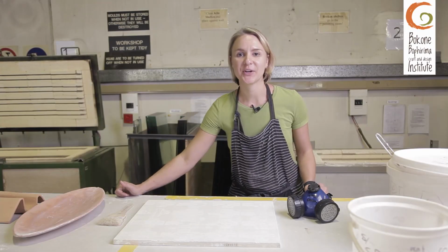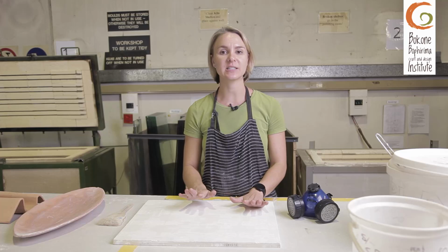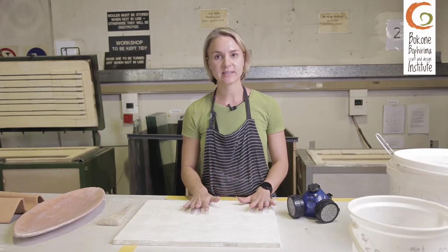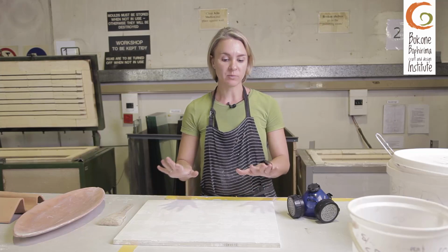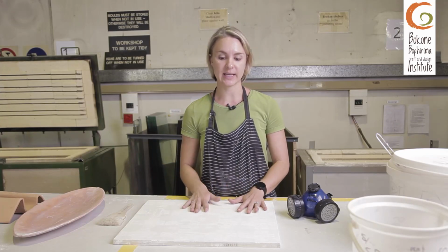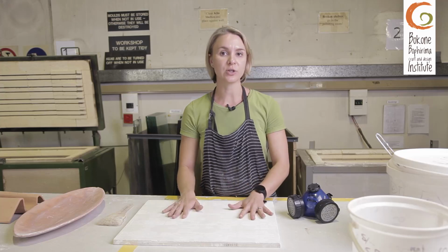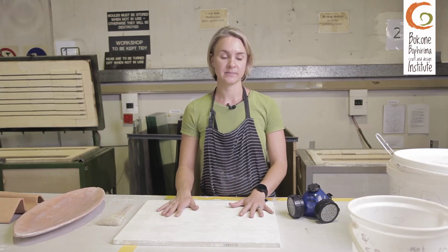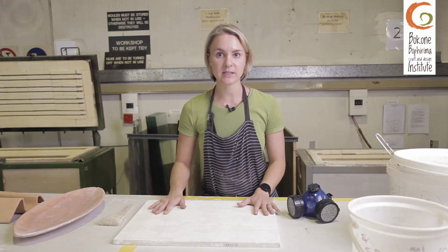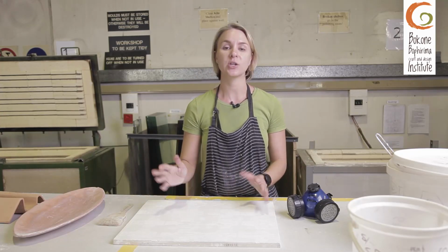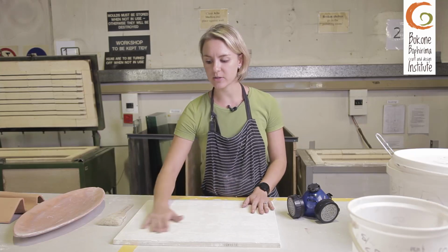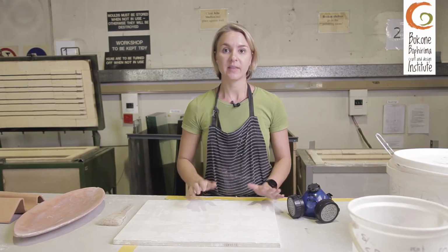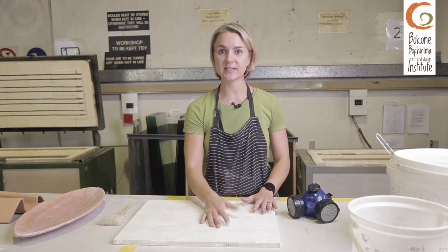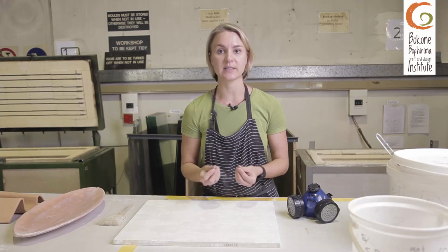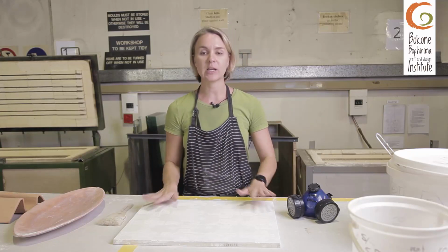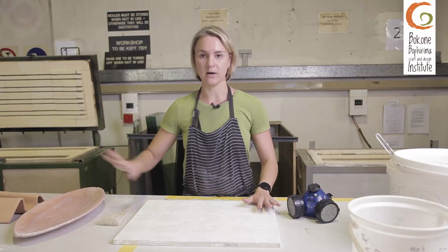Hi everyone, I'm going to discuss with you the application of applying plaster to your kiln shelves and your molds. The reason we do this is to make sure that the glass does not stick to the surface we are using in the kiln. I'm going to be showing the wet application, as when we do a wet application, you do not show any texture, it will create a smooth surface. One can also sieve the powdered plaster onto the surface, and this way you'll pick up a more textured surface if that is what you require. But for this technique, we want a nice smooth surface for all our molds.